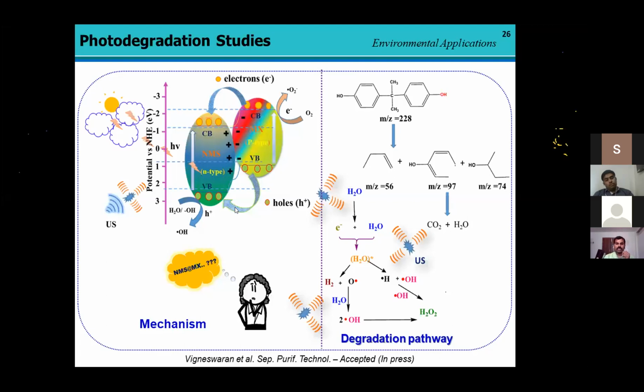We have also tried to degrade rhodamine B as well as phenol. Both work well on MXene-based material compared with graphene-based material, with higher efficiency and a lower rate of adsorption capacity loss than the other 2D materials also.